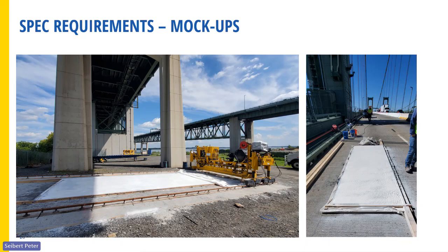As you can see here, this was a paver that was being used on the bridge. Use the equipment in the mock-up that you're planning to use on the project. We also had to do a second mock-up, you can see here, on top of the bridge, because there was a lot of concern if it's very windy, sunny, the slope, is the material going to flow from the vibration? Even though there's a speed limit posted, you all know when you go down the bridge that those trucks still fly at 70, 80 miles an hour, and there's a lot of vibration while you're paving. So to show that the material can hold the slope.